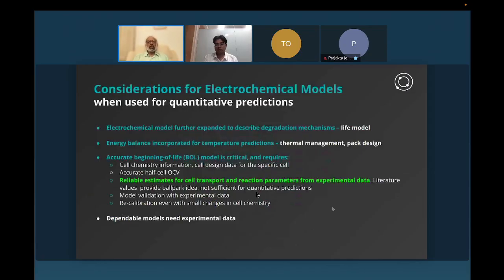So if it's an electrochemical model, here are some of the key considerations, especially when it comes to using these models for quantitative predictions. The models we saw, the processes we described, are for simple charge and discharge within a cell. The electrochemical models are often extended to describe the cell degradation. You describe similarly various degradation mechanisms. It could be particle cracking, it could be SEI layer. You build equations describing these, and that then eventually becomes the life model that predicts the life of the battery cell. You incorporate energy balance into these equations.